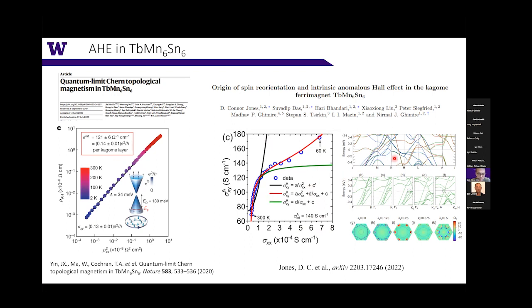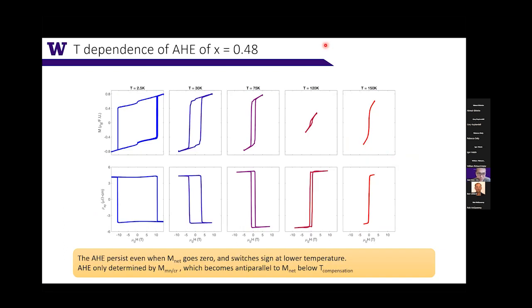So what do we find in the anomalous Hall? Let's first look at the temperature dependence, where we see this magnetization reversal. This is the same kind of magnetization versus H I showed you earlier, at different temperatures. You can see that the anomalous Hall is already pretty pronounced at high temperature, and even when the magnetization is about to vanish, you still have rather substantial anomalous Hall resistivity. But as you go to lower temperature, when the magnetization appears again, the sign of the anomalous Hall reverses. Now you have the opposite sign, and it remains strong all the way down to low temperature, with the same coercive field of the magnetization.